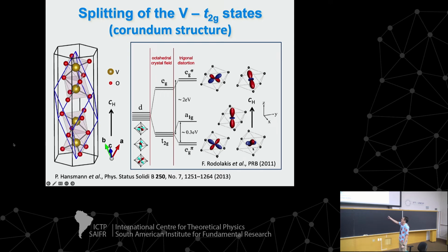What is it made of? So the vanadium atom, the last partially occupied levels are the d states. In the atom, the t2g states should be these that are here, but then in the octahedral and then trigonal distortion of the actual crystal structure of V2O3, what we will have is eg pi orbitals being the ground state, separated by about 0.3 eV from the a1g orbitals, and in particular the a1g orbital, which almost points in the crystallographic direction perpendicular to the hexagonal basal plane.